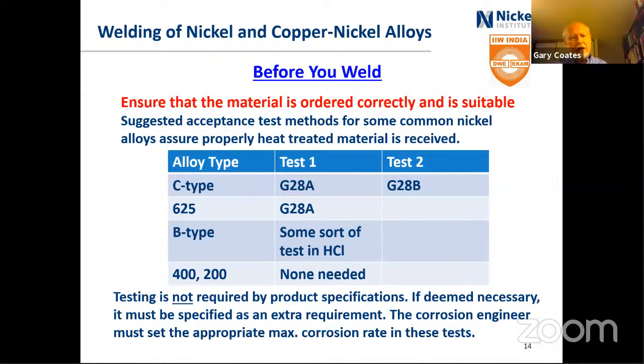When it comes to the B-type alloys, there is no standardized test there. Each producer tends to have their own test that they will check it against. But again, if you really want to make sure you're getting the right quality material, you have to specify the test and specify the acceptance criteria. And just as a comment, things like the nickel copper alloy 400 and the commercially pure nickel 200, they are simple alloys. They don't need to have a corrosion test.